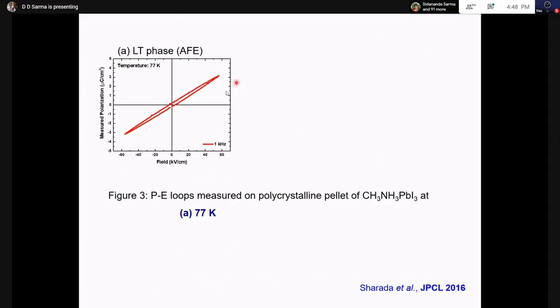Now, first of all, we don't see the loop, but before I say, aha, it's not ferroelectric, I draw your attention to the fact that I'm holding the material in the low temperature phase. Below 160 Kelvin, there is general agreement that the dipoles on the MA, the methyl ammonium, are anti-ferroelectrically coupled, such that I get only the paraelectric response from the PbI3 cage. This is the typical paraelectric response where the polarization is essentially linearly changing with the applied electric field: applied electric field this way, polarization this way, and there's essentially a single line going up and down.